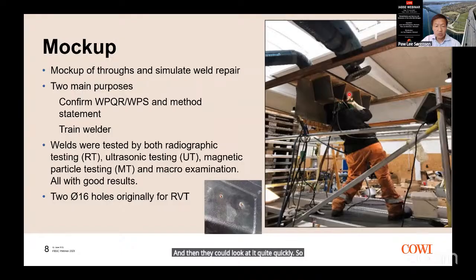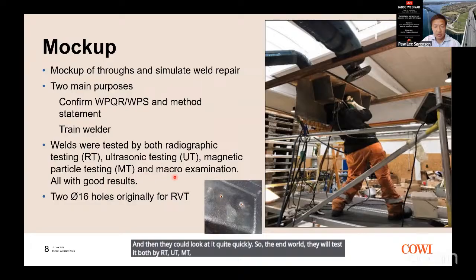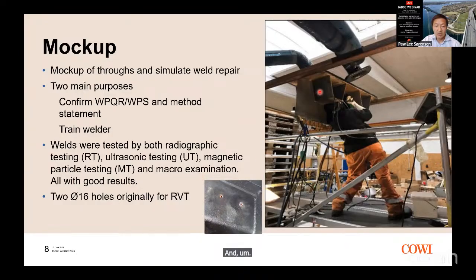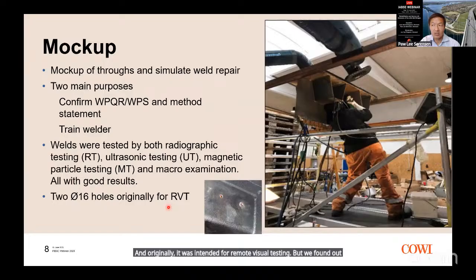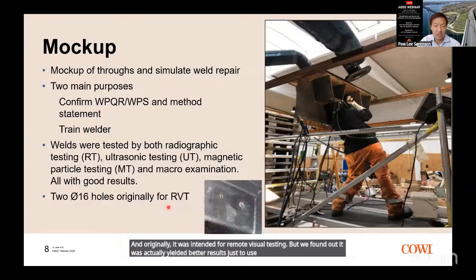So the welds were tested by RT, UT, MT, and macro examination. And during this trial, we also had the idea to drill 2 holes in the trough on the opposite side of the weld with 16 millimeter diameter. Originally, it was intended for remote visual testing, but we found out it actually yielded better results just to use a smartphone and a flashlight in each hole.